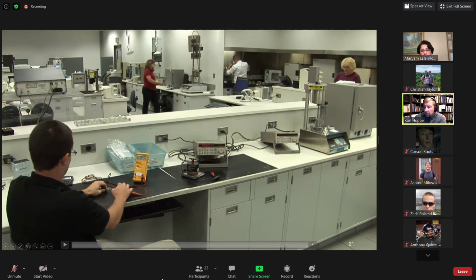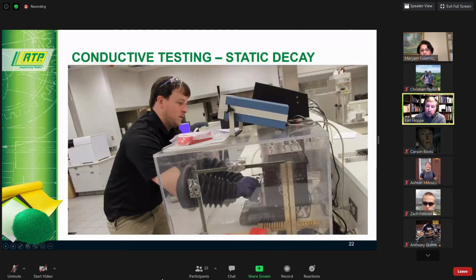We have a couple of other items here. So here in this picture, Brent is using a static decay tester. This is the conductive test that is measuring how slowly, making sure that the static is decayed over the correct amount of time. Not too fast, not too slow. There's a certain range there that needs to be met. So I put it in that chamber, and it's at a certain humidity. That's why it's enclosed there. There's a certain temperature and humidity that it needs to operate at. And so that's why you're in there with those gloves on.